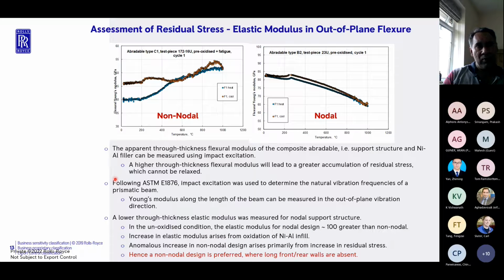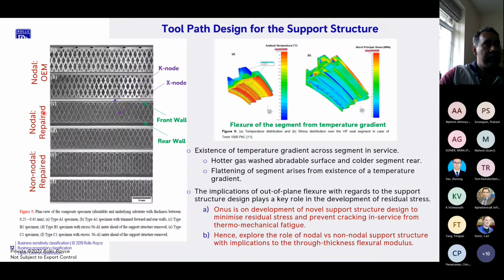We deposited abradables of two different designs. One was the repaired nodal design, where you still had the same design as the OEM condition. The only difference between the two being that this is repaired as compared to this being initially single crystal. The other design that we looked at was a non-nodal design. So effectively you had these loops. Clearly you do not have any K nodes, or the nodes that exist along the length of the abradable. At the same time, you do not have any internal X nodes. So this design was radically different to this design. And the question is, how do they perform in out-of-plane flexure?